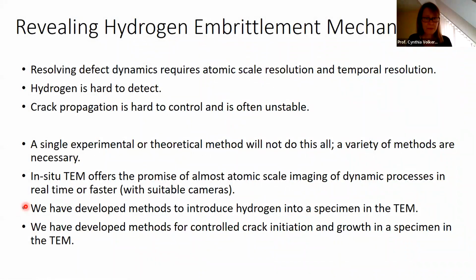What I'm going to talk about today are the methods we have developed to introduce hydrogen into a specimen inside the TEM. I'll also talk about our methods, which have taken us more than half a dozen years to develop, for controlled crack initiation and growth of a specimen inside the TEM, so that we can watch what's happening at the crack front. So that's what I'll start with, talking about those things. But before I do, the TEM is a powerful tool, and you'll see what it's good for when I show you the results.